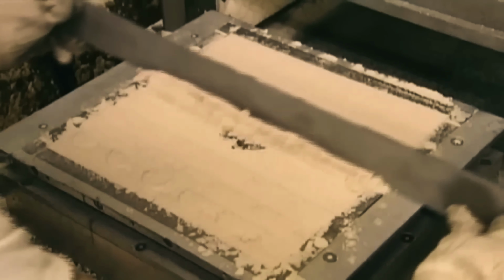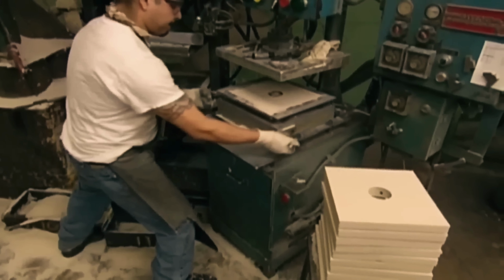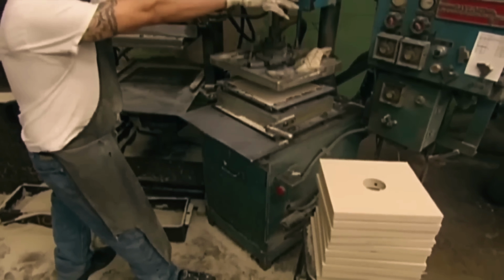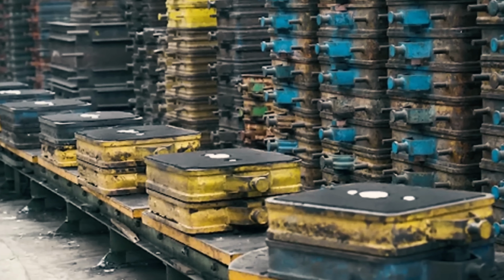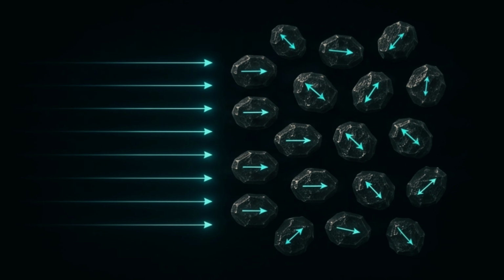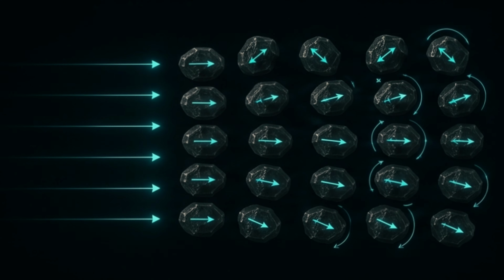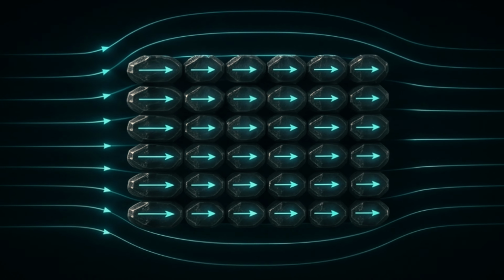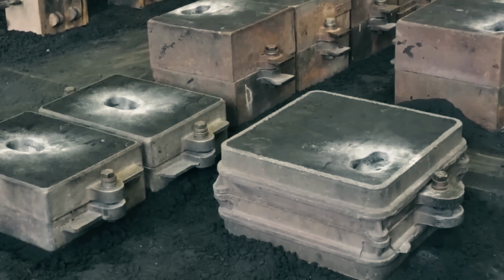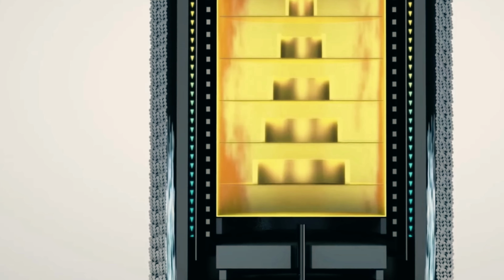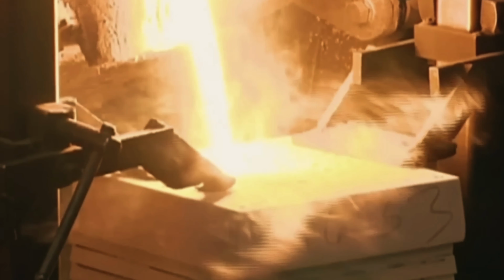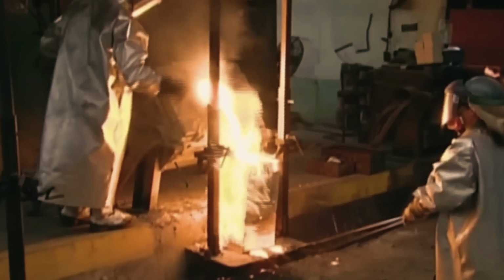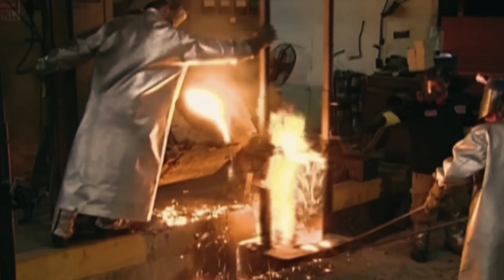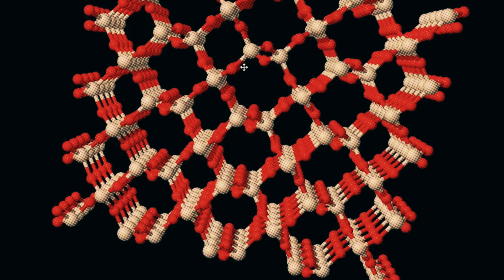Once the powder is fine enough, it's loaded into a mold and pressed inside an intensely powerful magnetic field, often tens of thousands of times stronger than Earth's own magnetic field. This is the single most critical step in the entire process. The external field physically forces every microscopic particle to rotate in place, twisting until each one points in exactly the same direction before the material is compacted and allowed to become solid. Get this step wrong, even slightly, and the finished magnet will come out permanently weak, no matter how well every other step is executed. There's no fixing a misalignment after the fact. It has to be right in that one moment, or the batch is essentially ruined.